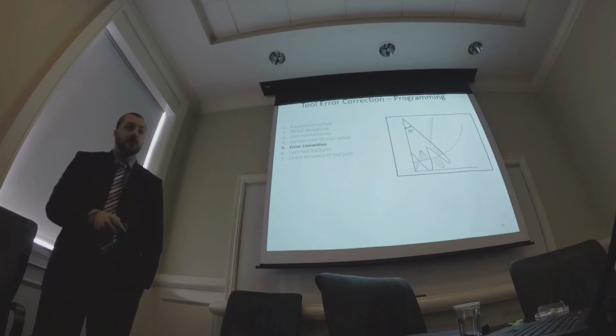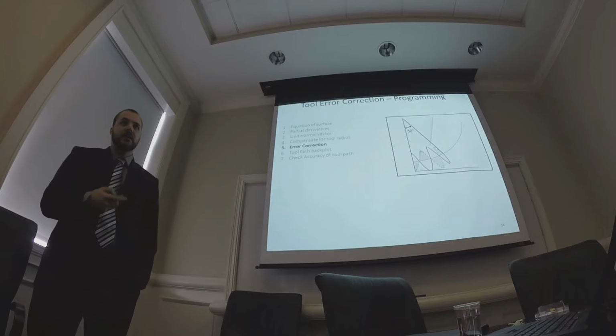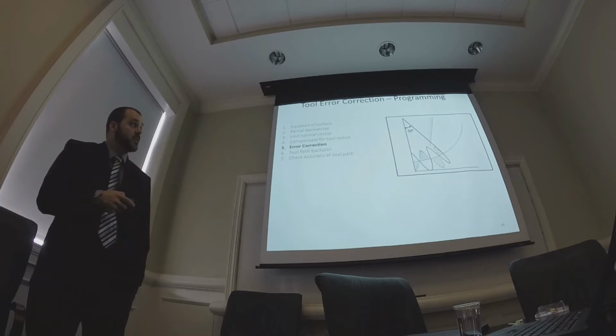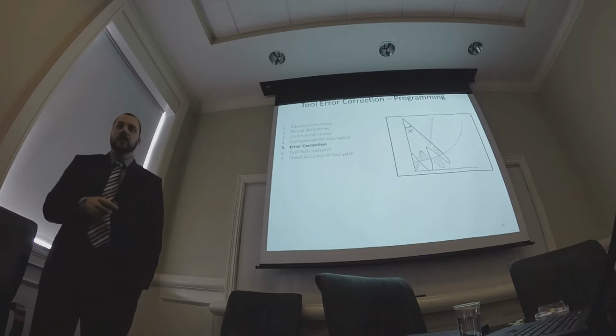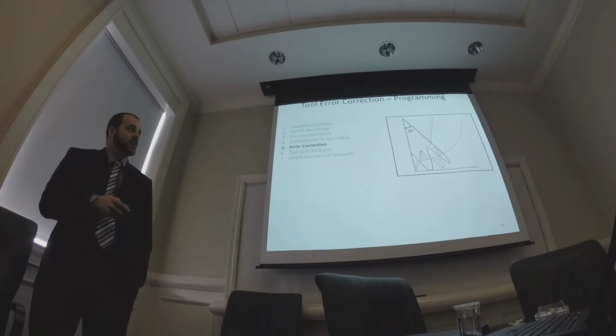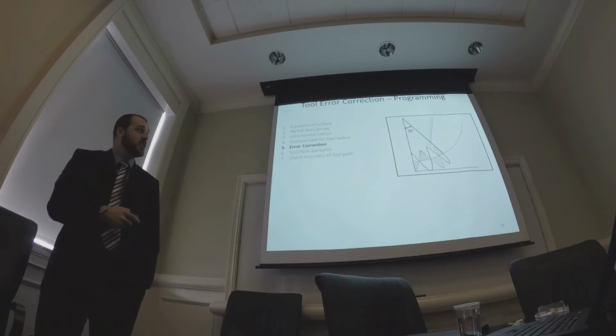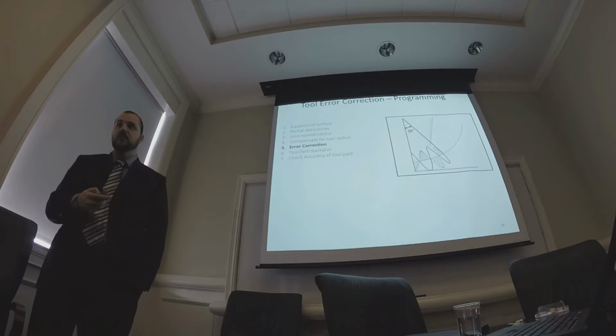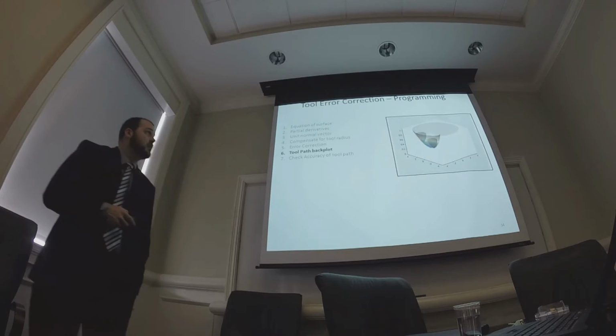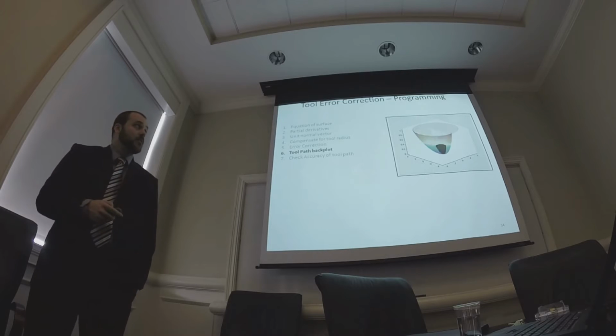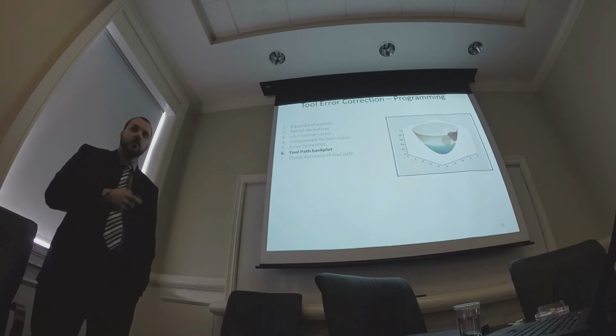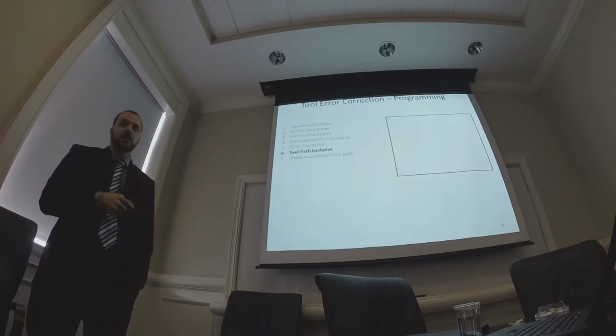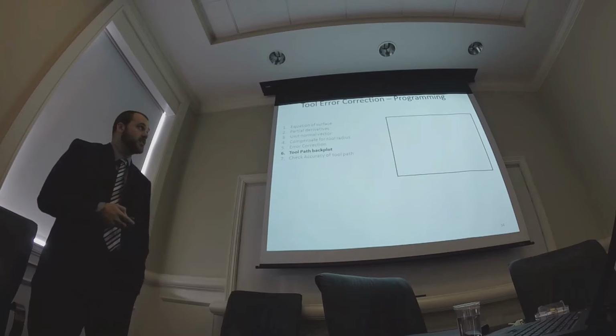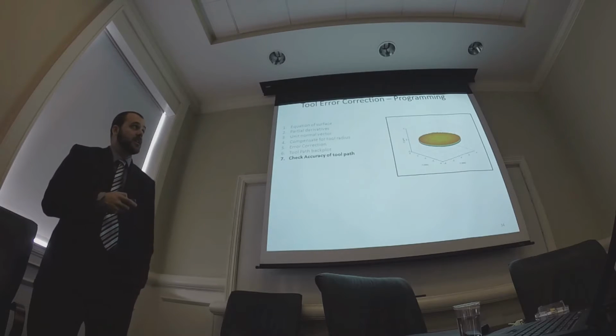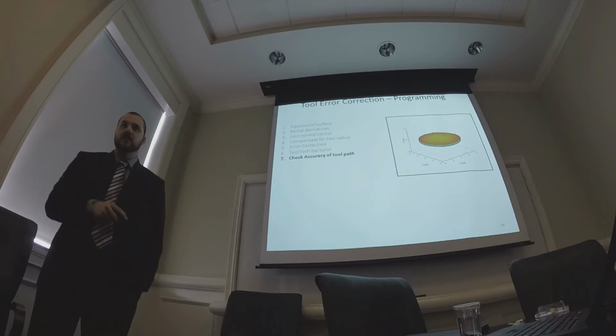We would then cut a sphere, get an idea of what the error correction was. The red would be some error that we found on the tool, and the direction of the arrows and the magnitude is how much correction in the unit normal direction we would need to make to correct for the waviness of the tool. Then we would take that tool with an error and the tool path that we would like to use, generate a simulated surface, remove the form, and then filter out surface finish, and we should get a nice flat surface at 0.